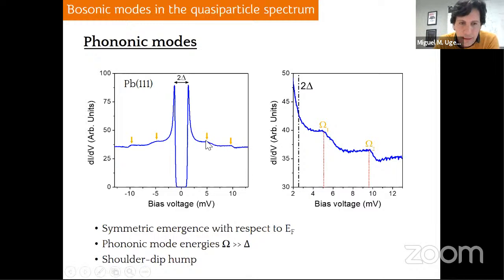In general, here you can see some shoulders and humps in the density of states of lead 111. This is the superconducting gap, and in a symmetric way as well, you can see some features that are phononic modes. Something characteristic about these phononic modes is that the energy at which they are found is in general much larger than the superconducting gap. Here you see that they lie well beyond 2 delta. I will tell you why this is important, but the energy at which you find these two features is well larger than 2 delta.